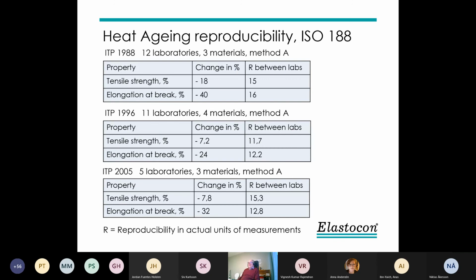Now coming back to interlaboratory test programs done by ISO. The first we see there is the one we made in Sweden in 1988. There we had a change in tensile strength of -18, elongation at break -40, and the R values are 15, 16. It's quite high. Then in 1996, we have 11 labs in ISO, so participants all over the world, 4 materials. We have less change in percent there. That depends on what materials you use and what temperature you choose. But the R values are still quite high. It's a little better, but not very good.